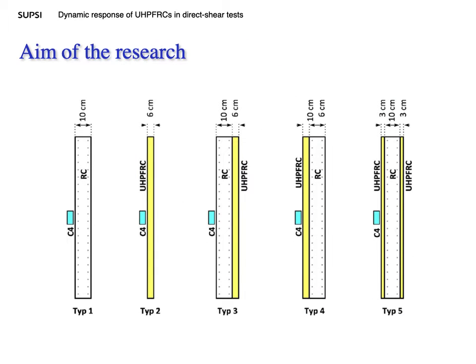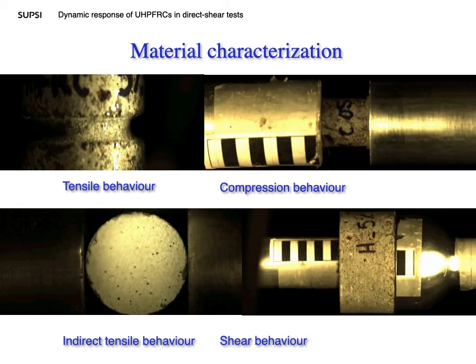research was study the retrofit system using ultra-high performance concrete. When a critical structure has been designed without any blast protection, it is necessary to improve its resistance capacity by means of retrofitting. Usually, we have characterized the material in a different failure mode like tension, compression, indirect tensile, and shear behavior. And in particular, now we are concentrated in shear behavior.